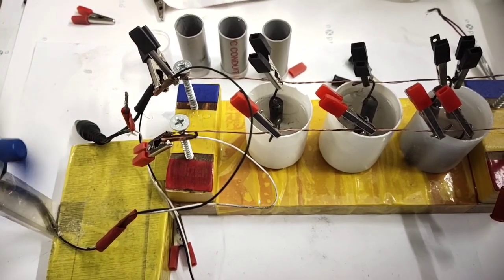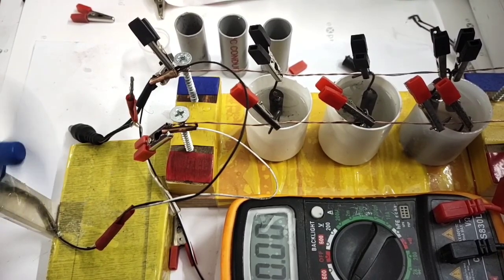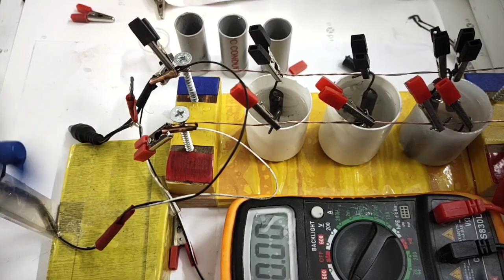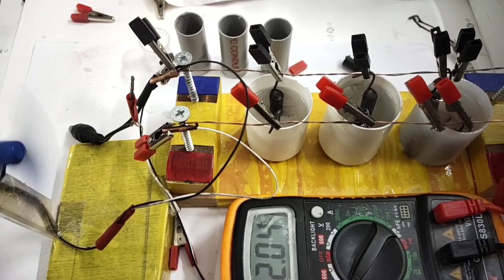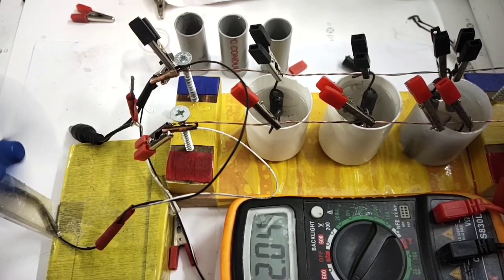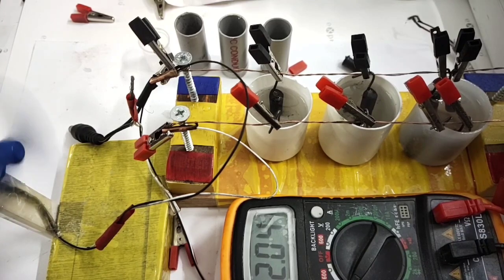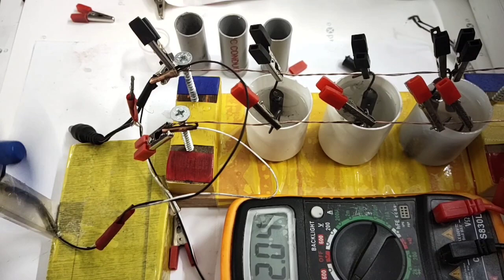After discharging again, we will go for second forming one hour again. This process will repeat. Then next time we will go for charging. The process of discharging for 10 minutes, almost 2 more minutes is remaining. So I am going for second forming now. After second forming, I will discharge for 10 minutes, and then I will take all those electrodes and fit into the smaller vessels. There I will go for final charging half an hour.